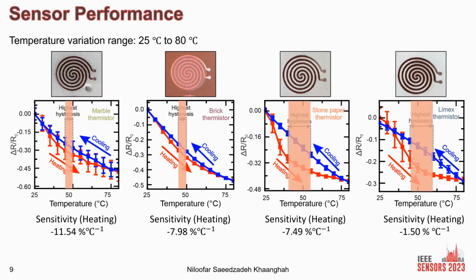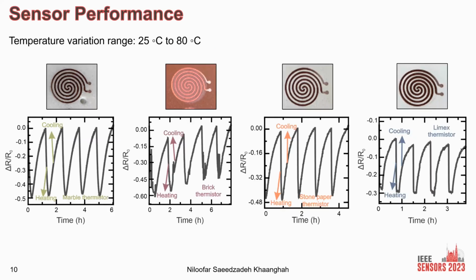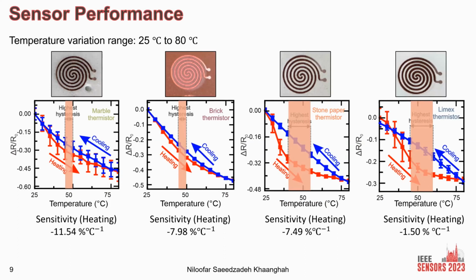If you look, the 2 rigid thermistors have smaller hysteresis compared to the stone paper and the Limex thermistors. And by taking a linear approximation of the plots, we can get the sensitivity, and the sensitivity of the marble is larger than all the thermistors. This is due to the high thermal conductivity of the marble thermistor compared to the others, and also due to the nature of the stone paper and the Limex thermistors, because they are polymer based and we don't know exactly what happens at higher temperatures.